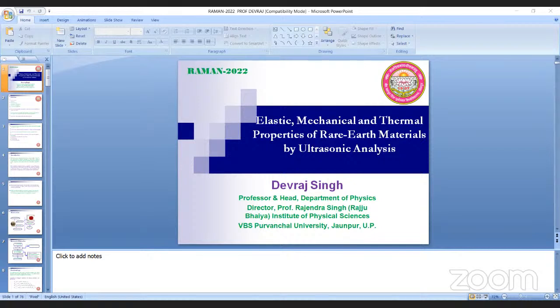The essential parameter for finding the elastic constant is the lattice parameter. As you know, for a student of solid state physics or solid state chemistry, this is taught in both. For the lattice parameter, we use the simple nearest neighbor distance. In our case, the nearest neighbor distance is half of the lattice parameter, R0 equal to a by 2. In other cases, especially FCC metals and BCC, this is different for the different types of structure.